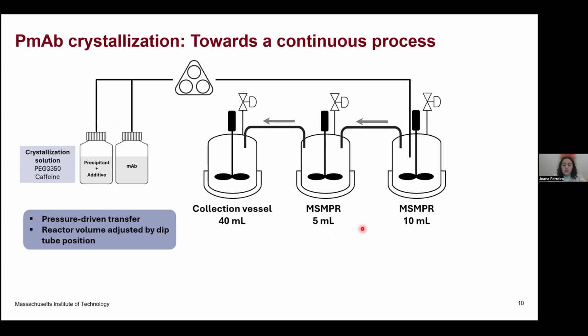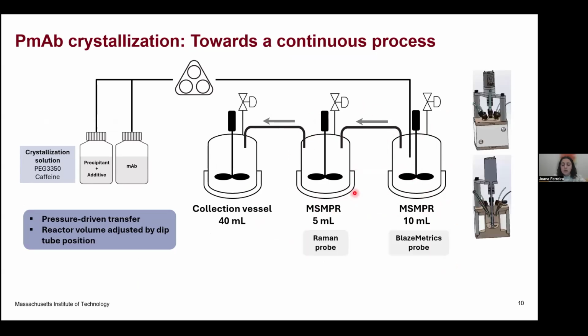In terms of the setup, we have 3 different MSMPRs. The first one on the right-hand side is where we run the batch process. Then we transfer the material to the second reactor, and we do this because we have different probes. On the first crystallizer, we have the Blaze probe, where we can get some inline information. Then we transfer the material to the second one, where we have the Raman probe, and then we have our collection vessel. After running the batch step, we start pumping the material.